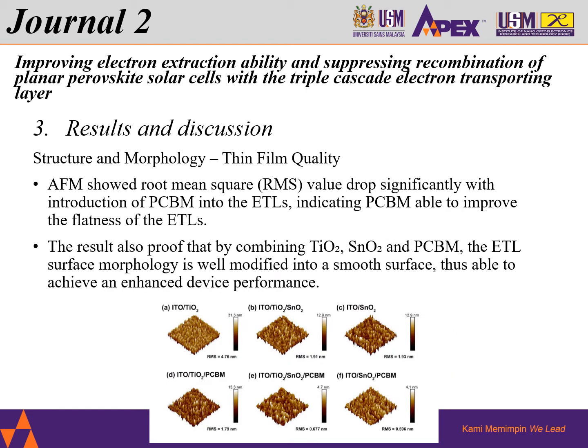From the AFM, we learned that with the introduction of PCBM into the ETL, it is even better to improve the flatness of the ETL. So this result also proved that by combining 3 layers, the ETL surface morphology is still well modified into a smooth surface and able to achieve an enhanced device performance.